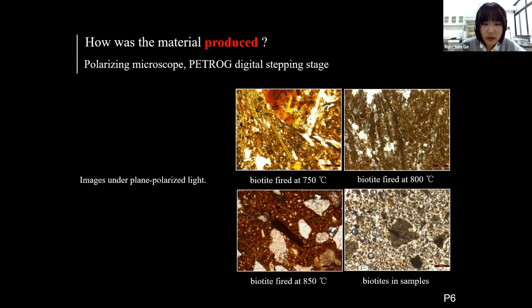Has it been fired? We used polarizing microscopy to provide evidence for the firing temperature. Dark brown biotite, an important mineral in potteries, is found in samples with cracks being observed, like the 4th picture. According to simulation samples, when potteries are fired to 850 degrees, biotite cracks will appear in the mineral, and the mineral will become darker, like the 3rd picture. In contrast, not much phenomenon was observed for biotite fired below 850 degrees. So we suggest the adhesive material was fired at a high temperature, at least above 850 degrees.